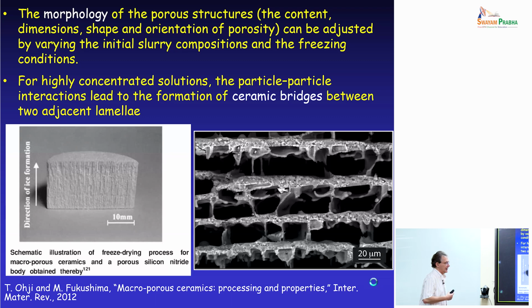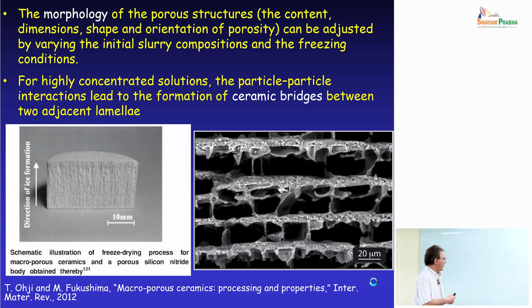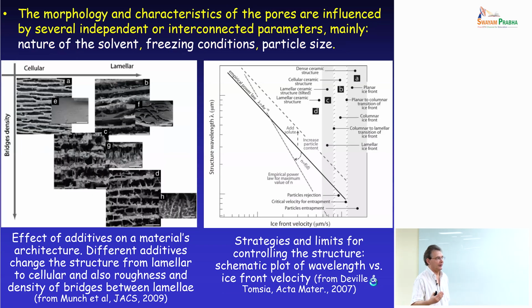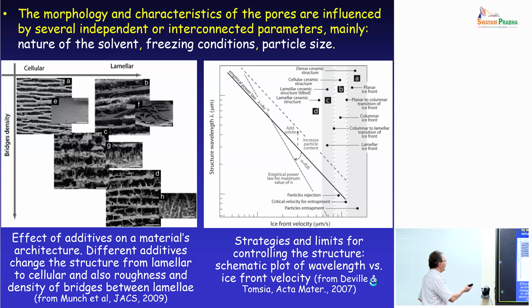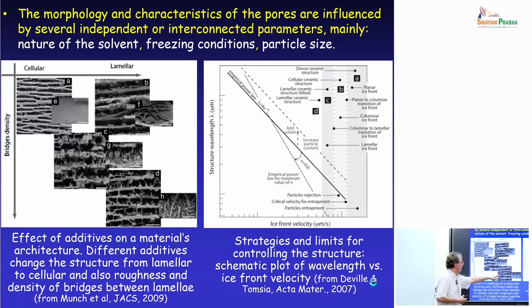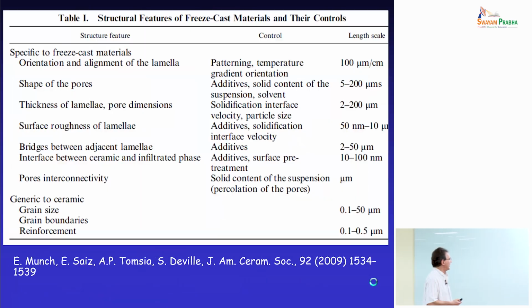For instance, in Japan, there is a company making thermal insulating blocks based on silica using this approach. They are very efficient, and it's a very cheap approach because you're not burning out anything. You're simply sublimating ice. And there are different ways of controlling the shape of the ice crystals. For instance, you can go from a lamellar structure to a structure where you have some bridging parts that lead to a more isotropic behavior for the material.